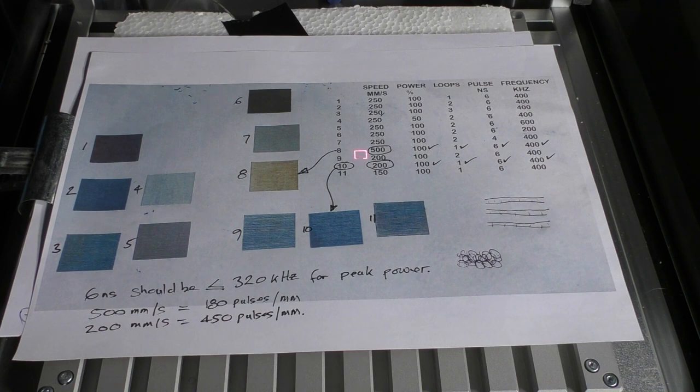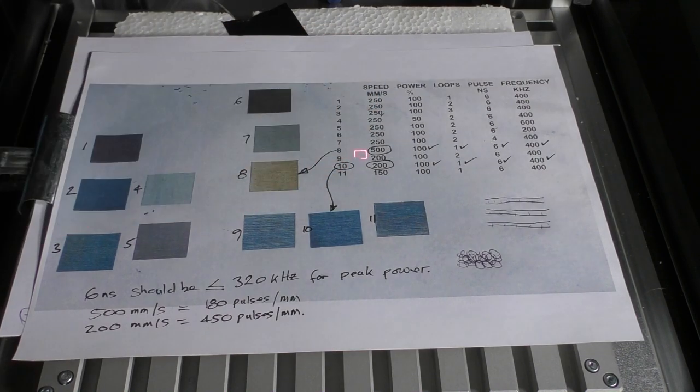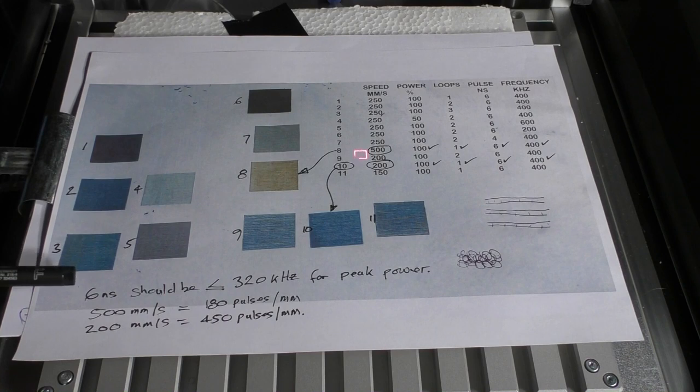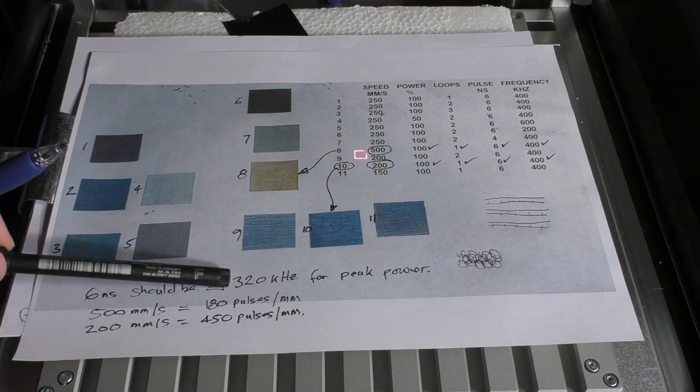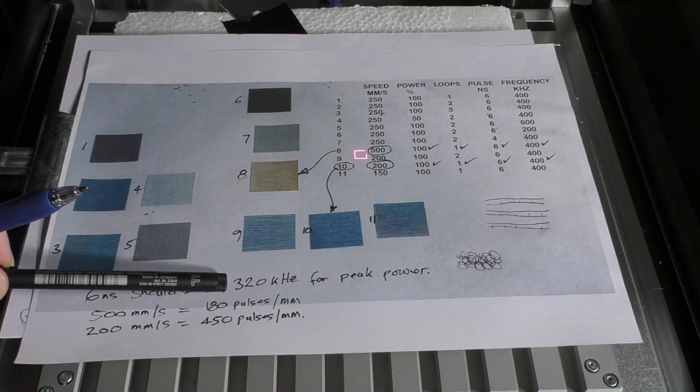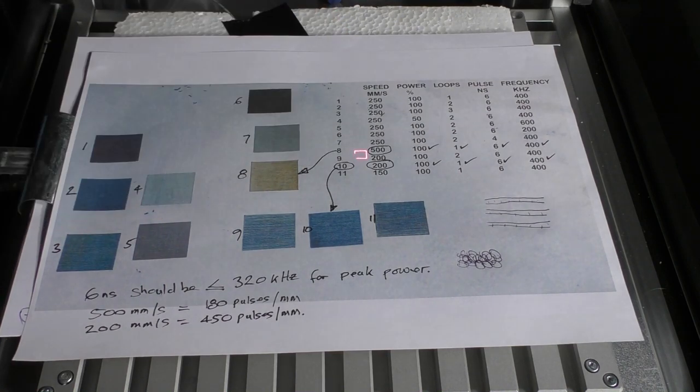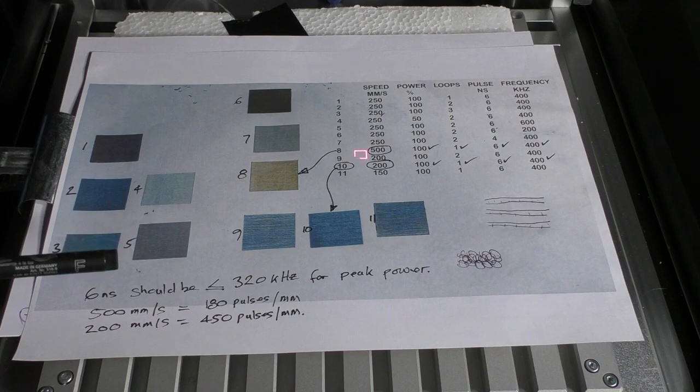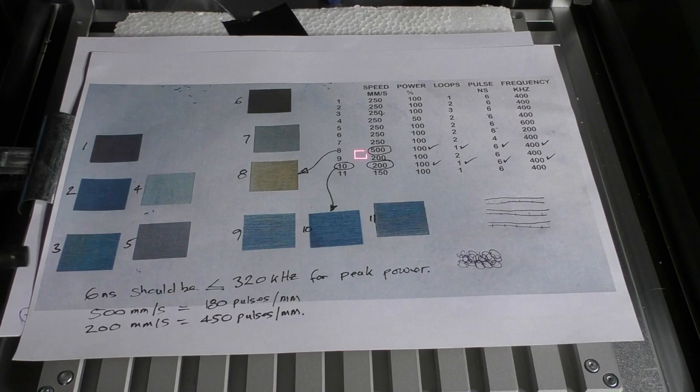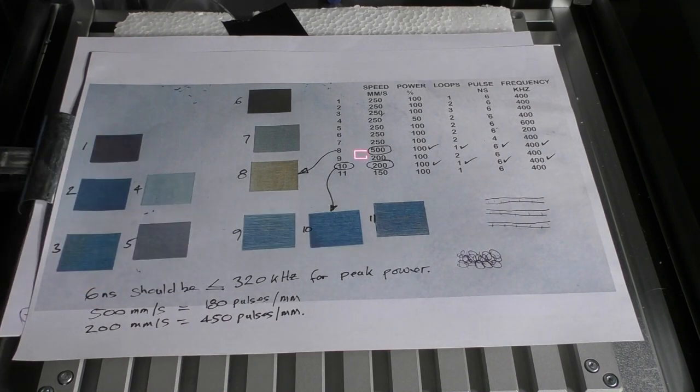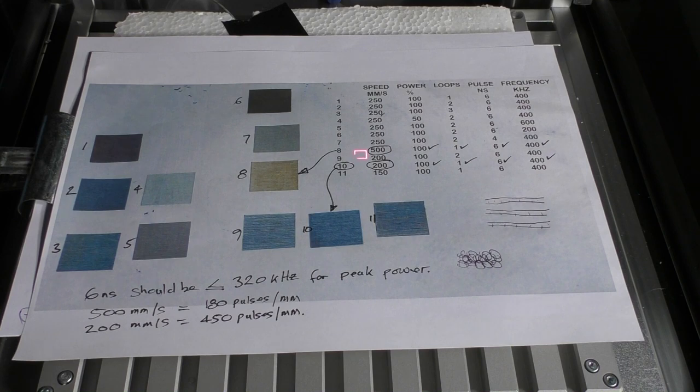Now I have to also add that for six nanoseconds, which was the critical factor that I was using, I wasn't actually using the correct peak power. I should have actually been using 320 kilohertz for peak power. So 400 kilohertz means I'm running faster than I should do. That probably means I'm not allowing all the electrons to be promoted to their excited state before I push the pulse through and try and get to peak power. So that probably gives me another way of controlling the power into each pulse. So we've got several strategies that we can adopt.